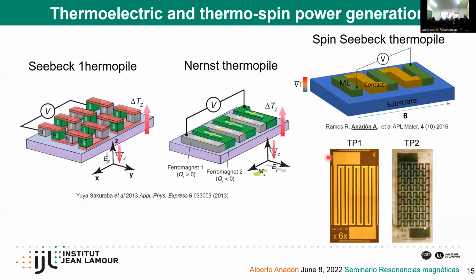First, we used one device in which we had in series a magnetite-platinum system and a gold contact. So in this case, we can sum the voltage of all these different magnetite-platinum terminals, let's say. So our goal here was to have a much higher voltage output in the end.